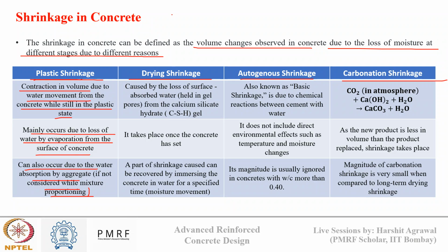Okay, and if it is not taken care of, then plastic shrinkage issues can arise. The second type is drying shrinkage, which is caused by loss of surface absorbed water by the calcium silicate hydrate. Okay, this is drying shrinkage, and it takes place once the concrete has set. So the shrinkage that happens before setting is known as plastic shrinkage, and the shrinkage that happens after setting is known as drying shrinkage.